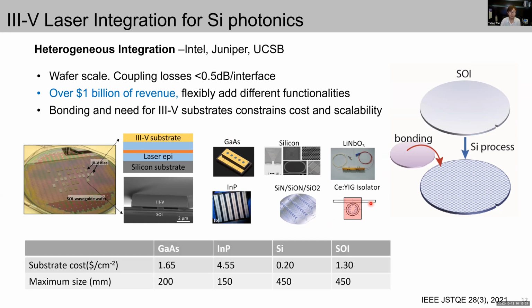However, the associated technical complexity is still considerable, particularly with respect to the stringent requirement of an ultra-clean and extremely smooth surface before the bonding. Moreover, you have to use a III-V substrate that is costly and imposes a limit on the maximum bonding size set by the largest available III-V substrate, which is typically no larger than 200 millimeter for GaAs and 150 millimeter for indium phosphide. This is much smaller and more expensive than a silicon counterpart.